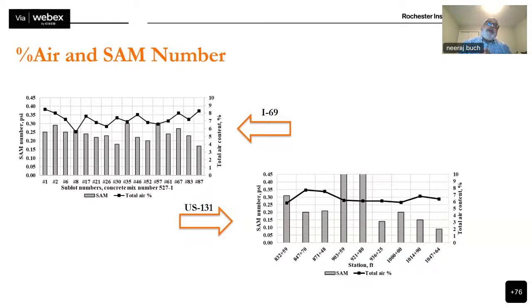Moving on to the durability properties. We measured the volume of air using the conventional air meter. And remember, the target was 6.5%. The tolerances are usually plus minus 1%. So you're looking at anywhere from 5.5 to 7.5 or 8% volume of air.